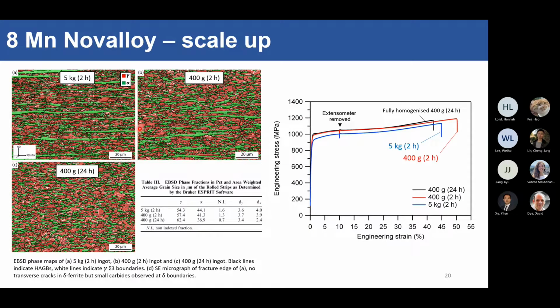So we can see in the homogenized steel, so 2 hours in the big ingot and small ingot, you can see these very long green lines here. And that's your delta ferrite. So delta ferrite is sort of a little globule. And then when you roll it, it just goes, and it forms these very long, what we call delta ferrite stringers in your steel. And this steel here, we've homogenized it for 24 hours.